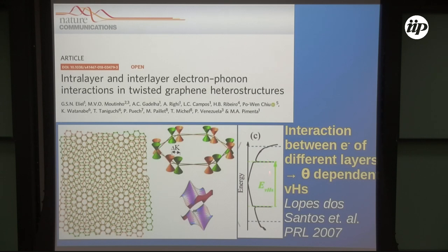What's the main interesting thing about this is that when you have twisted bilayer graphene, you have singularities in your density of states. And the position of the singularities depends on the angle. So if you change the angle, you change the electronic structure of your sample. So this is very interesting. For instance, very recently, they went to an angle of approximately 1.1 degrees, and they saw superconductivity, because they are changing the electronic structure, and then in this particular magical angle, these two singularities coalesce here, but I don't want to talk about this very much today.